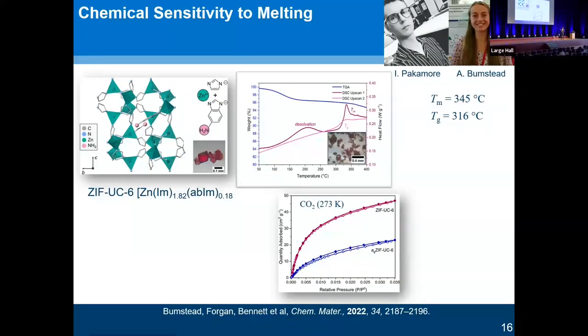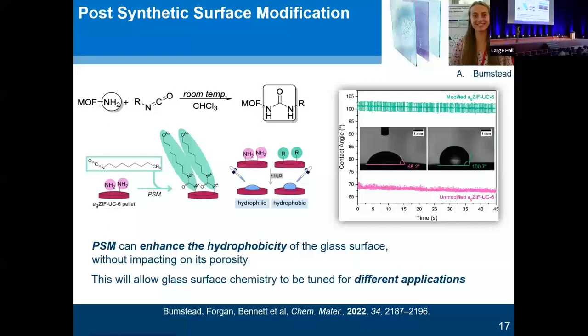Alice Bumstead in the group has done some beautiful work functionalizing the glasses. So we can make new ZIFs with things like amino benzimidazole ligands in them, giving them a nice red color. They melt at around similar temperatures, around 350. And importantly, your carbon dioxide uptake at very low pressures is about half that of the crystalline equivalent. So we're not actually looking at these glasses to store carbon dioxide, but in terms of separation, this should now get people thinking. Why did Alice choose amino benzimidazole to functionalize?